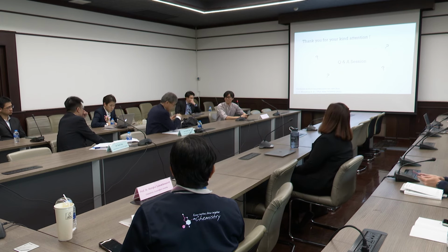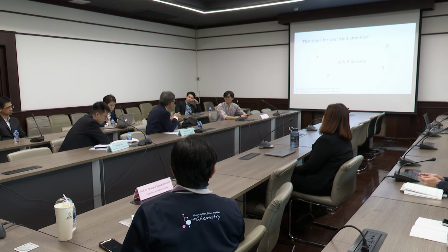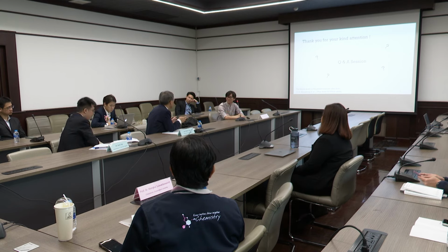Yes. But on the other hand, bulk modulus has a bit different behavior. Well, actually, when we have the vacancy in the system, in particular the boron vacancy, some elastic constants for this material system change significantly, and some of them drastically drop. Those that drop will be reflected in the bulk modulus. That's why the bulk modulus constantly decreases when you increase the number of vacancies in the system.